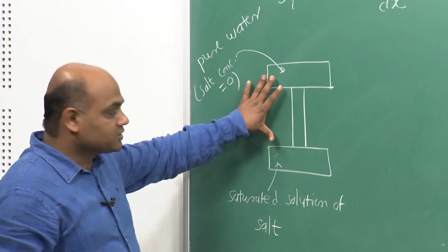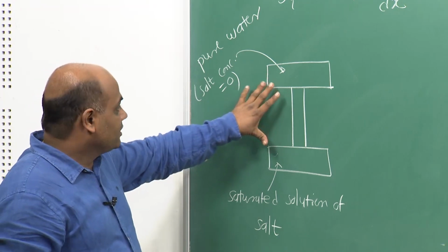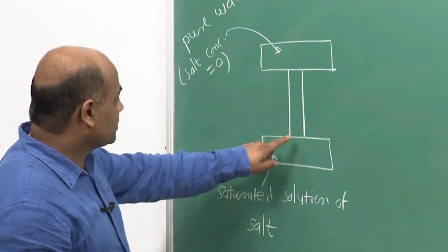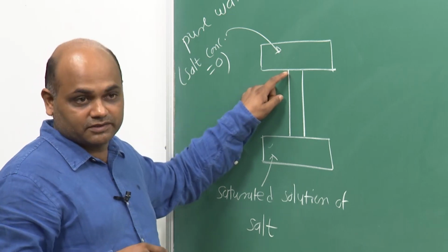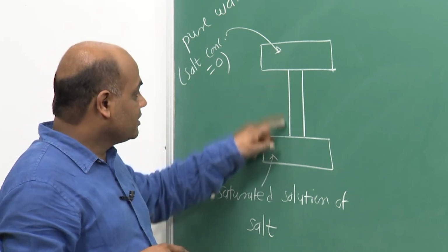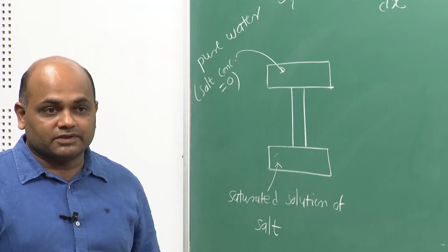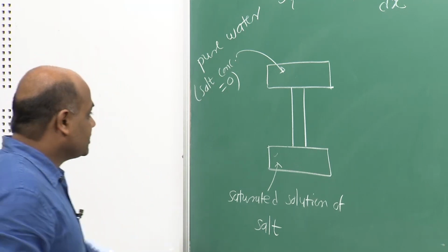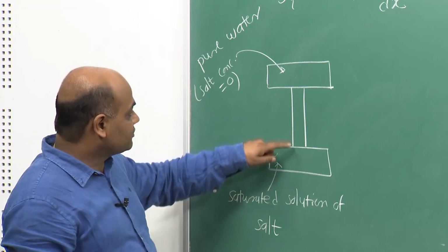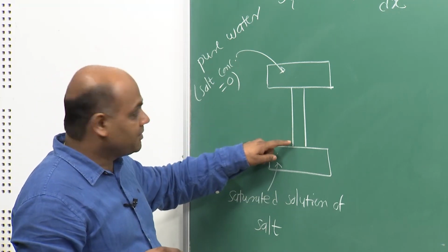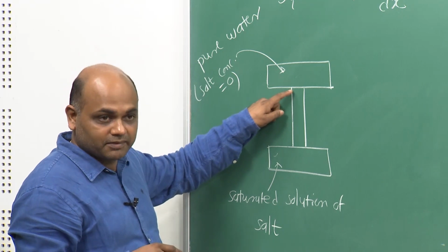And what was the purpose of these two? So that the concentrations at the two terminals of the tube were maintained constant. This way he could develop a steady state condition for diffusion. Steady state means the concentration, as the diffusion occurs, obviously there will be a concentration gradient which will be developed, right.